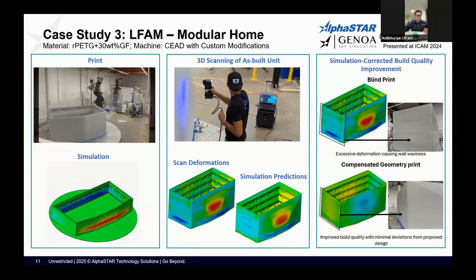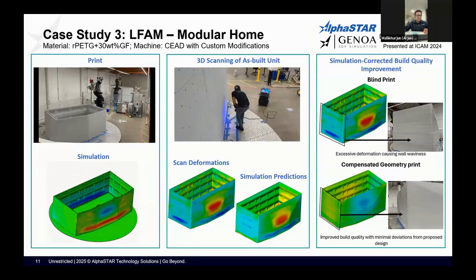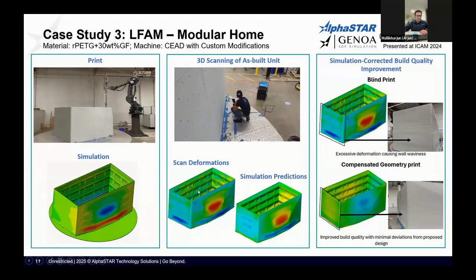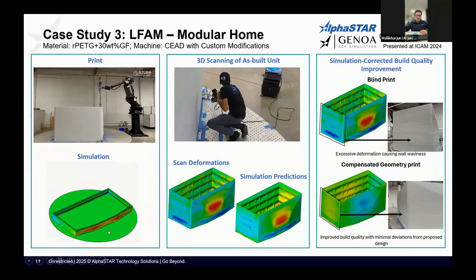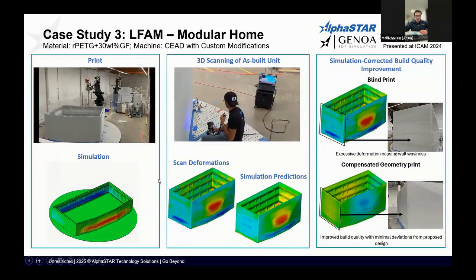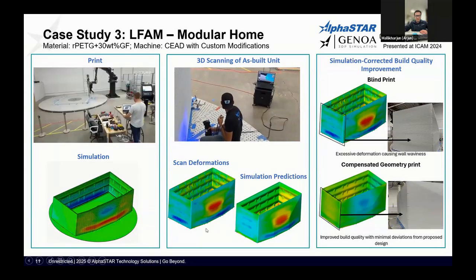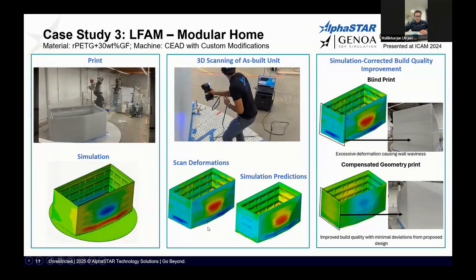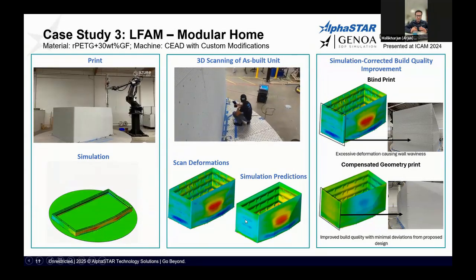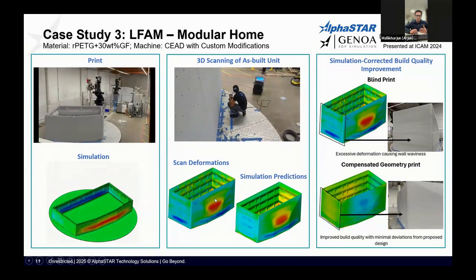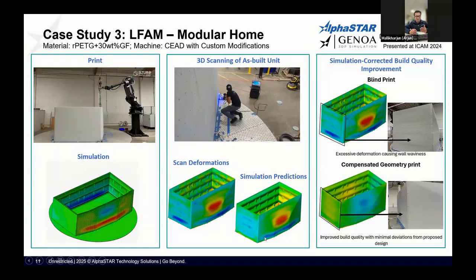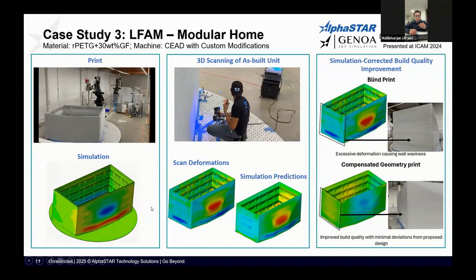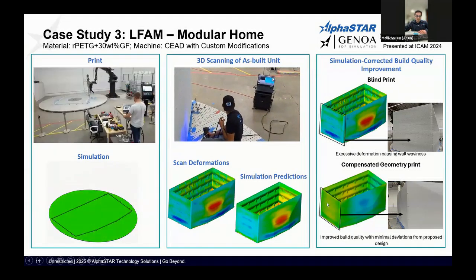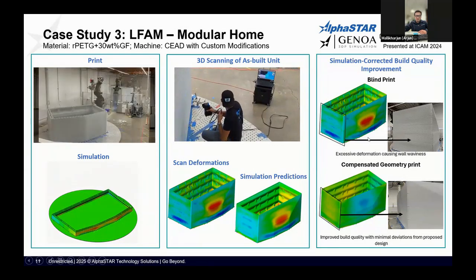We simulated it going from left to right again. The video shows the print, and the bottom is the simulation, bringing in the hybrid GCode from the GCode and the controller. To validate our predictions, we scanned the geometry just to showcase that, yes, the simulation is able to pick up all the details. So the scan deformations are from where we actually printed this geometry and scanned it, alongside the simulation predictions, where you can see that, again, because it's large format, these blues and reds are gigantic numbers. Blue is bowing in a lot, red is bowing out a lot. So in this case, simulation is able to pick up all those details as close as possible to the reality.